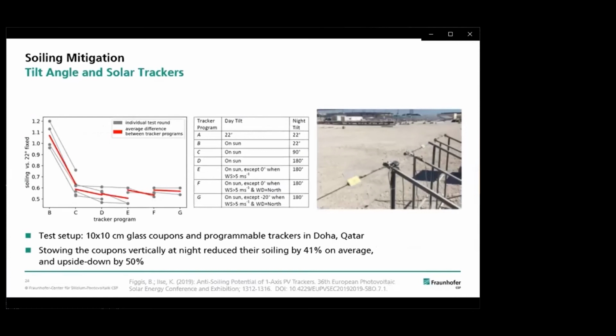Here I want to show some of the outdoor results, which we did on small glass samples, comparing different tracking algorithms, starting with a reference here called B. And when we put the glass samples to 90 degrees during the night and also to 180 degrees during the night, while they were tracking the sun during the day, we had an average soiling reduction of 41% for vertical and up to 50% for upside down.